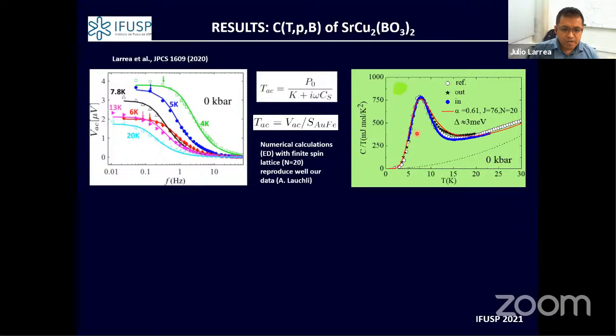Knowing that our measurement has very reliable data, we can proceed to calculate the energy gap associated to this shape of the specific heat, in the order of 30 Kelvin, and also the exchange coupling constant related to the dimer singlet state. Theoreticians help calculate this gap and other parameters through exact numerical calculation.